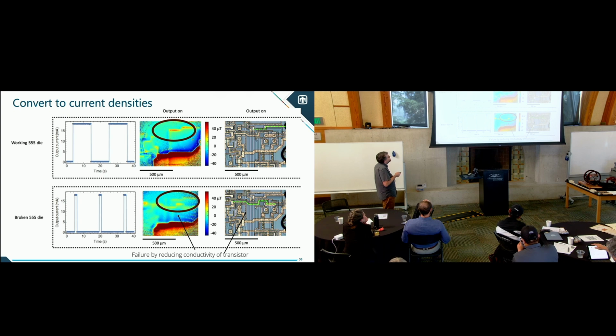So here you have the current flowing here, which corresponds to this line. And in this case, you actually have much less current going through that path and a little bit extra through this channel right here. These measurements were performed by Polly. I actually taught myself COMSOL to do the simulation. And what I found is that if I tweaked the conductance of this transistor here, that would be consistent with this failure mode in this device.